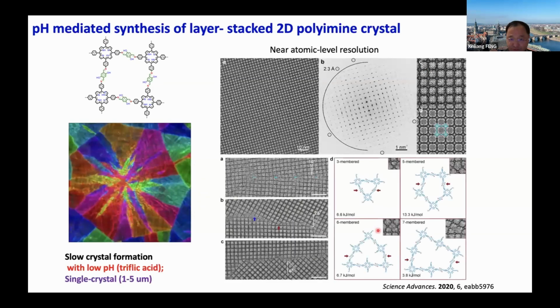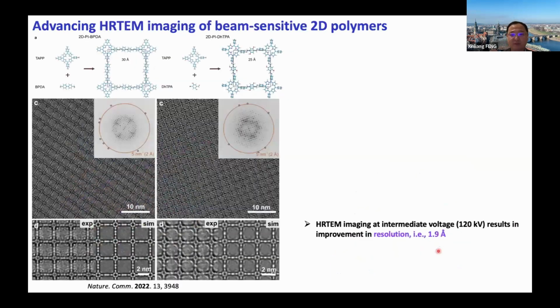And of course, we can also further push to understand the structures under different materials, like in this case, the polyimine, for example, which we can also make a few micrometer single crystal size. And with the TEM, we can even go to near atomic resolution, with the very crystalline structures, and even allow us to go to the grain boundary to understand the defects, like 5-membered, 7-membered rings, which are more defective structures.